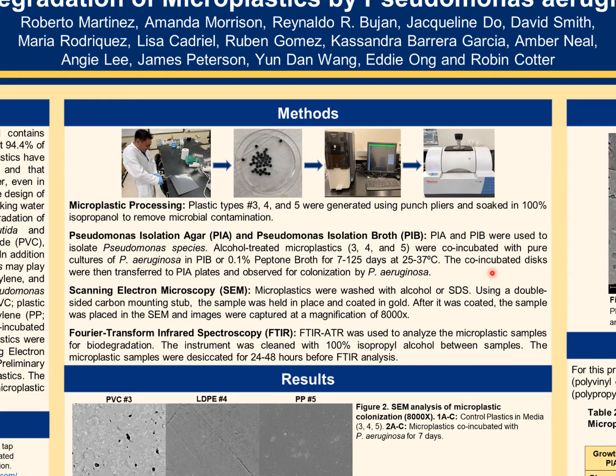Pseudomonas Isolation Agar and Pseudomonas Isolation Broth were used to isolate Pseudomonas. Alcohol-treated microplastics 3, 4, and 5 were co-incubated with pure cultures of Pseudomonas aeruginosa in PIB and 0.1% peptone broth for 7 to 125 days at 25 to 37 degrees Celsius. The co-incubated discs were then transferred to PIA plates and observed for colonization.